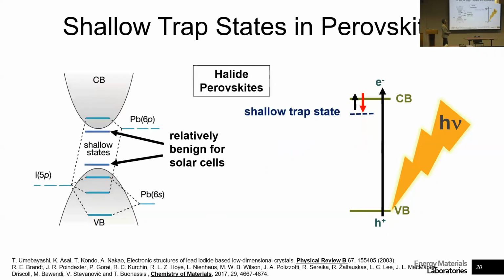In perovskite solar cells, what we have found over the years is that the defects formed from the impurities from processing these materials very cheaply, very rudimentarily, form shallow traps, very close to the conduction band. That state is so close to the conduction band that with just thermal energy, about 25 millielectron volts at room temperature, the electron can go back into the conduction band. This process is what we call trapping and detrapping. It gets trapped, it gets detrapped, but the electron is available to move around. So even with a lot of defects in our material, we're able to get really high quality semiconductors.